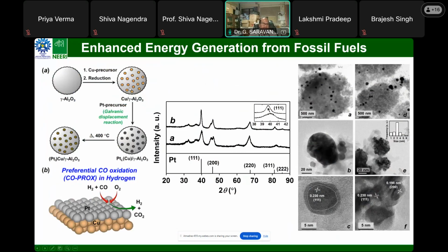What we have done is develop copper surfaces through galvanic reaction. Because of the favorable surface redox potential, when we mix with the platinum precursor, the platinum salt is deposited on the copper surface, and eventually upon heating you get different structures. As usual, we do typical characterization, both XRD and TEM, to ensure that the structure is formed.